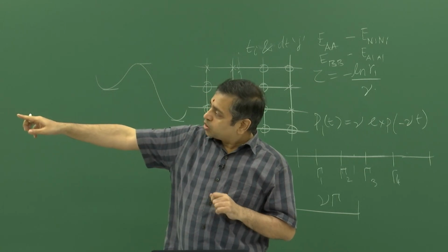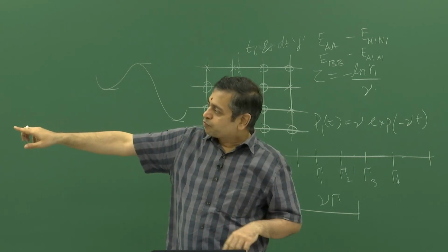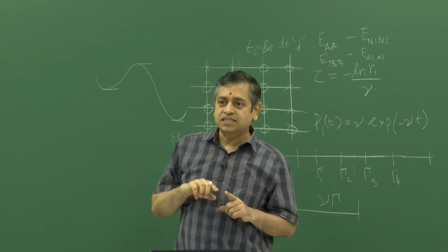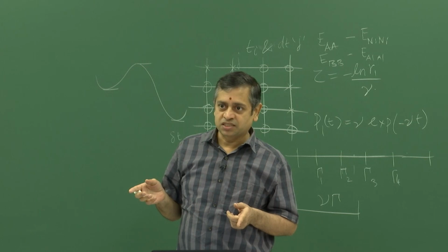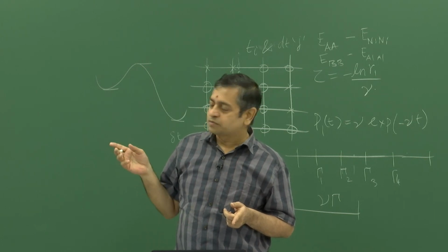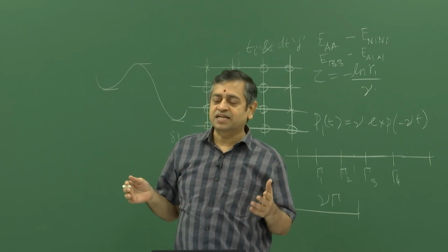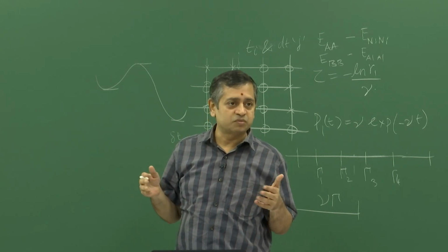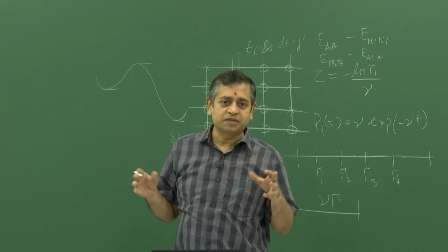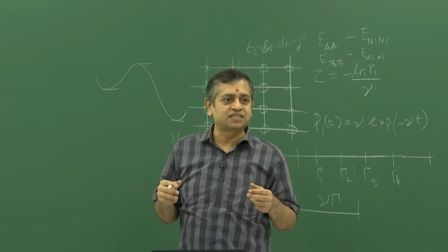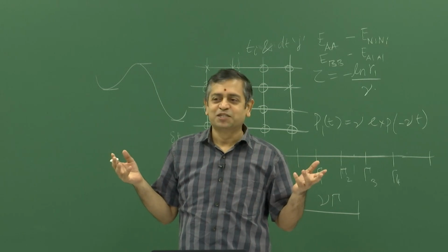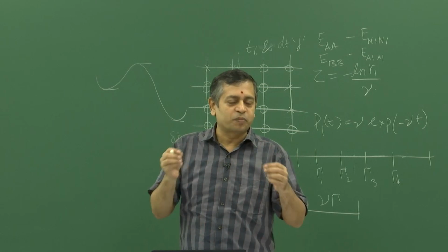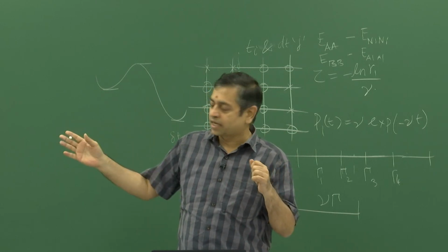Now, if you know the vacancy formation energy, you can also evaluate the vacancy-A atom interaction energy. The assumption made is that the vacancy interaction energy is considered to be 0, which makes sense because you can consider empty space as consisting of all vacancies. Like I said, there is nothing like a vacancy; there is a site which is not occupied, which we think of as a vacancy.